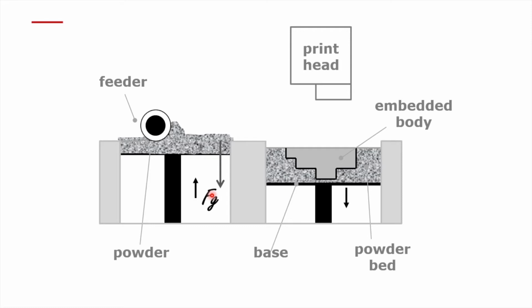When the particles get smaller, the force gets smaller, while the particle-particle interaction is not scaling directly with the particle size. So from a certain particle size, the gravitational force acting on the particles will be smaller than the particle-particle interaction. And then it's definitely the point where the particles no longer pack well.